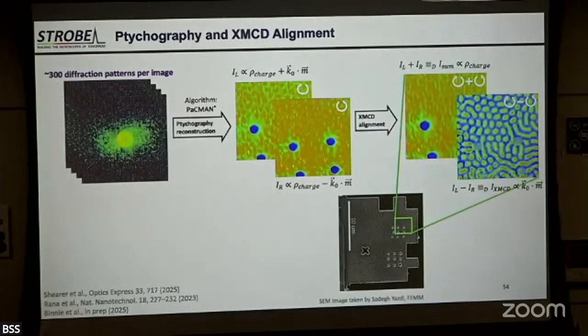First, you have to make sure exactly what you're seeing. Are you seeing good magnetic contrast? So what you do is you take your left and right circularly polarized images, you add them and then you subtract them. When you add them, you make sure in each 2D image that you're not seeing any skyrmion-like structures, and they only come when you subtract them. Then you're getting the magnetic contrast.